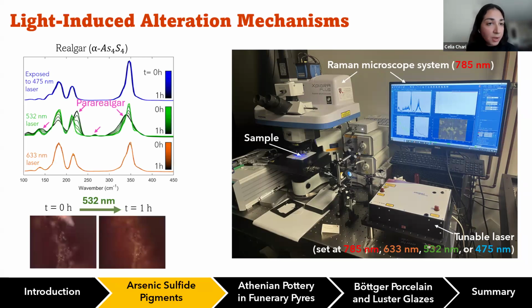Here are some examples of realgar with the spectra as a function of time after or during the exposures to blue light, green light, and amber light. I didn't include red light 785 because there is no change in any of the arsenic sulfides that I've been seeing. So they are not susceptible to change when exposed to red light. But as you can see, green light specifically is the one that is causing the formation of para-realgar, given enough time for it to form.